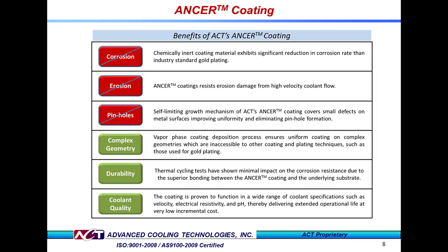Repeated thermal cycling tests have demonstrated superior bonding between the ANCER coating and the underlying copper substrate without impact on corrosion resistance. The superior coating strength and durability allows a wider range of coolant specifications of flow velocity, dissolved oxygen, and pH, allowing more relaxed operational requirements without affecting MCC performance. So there are the major advantages of ANCER. Let's now look at some testing results to explain why we are so excited about this new solution.